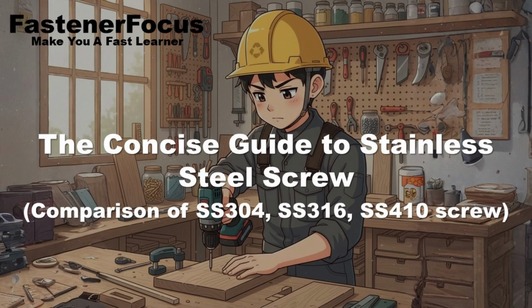So if there's no oxygen in that tight, salty gap, the self-healing passive film cannot reform itself. Exactly. The local chemical conditions inside that tight, oxygen-starved, chloride-heavy crevice change drastically. The trapped water becomes increasingly acidic, and the corrosion rate skyrockets. It's a localized, acidic microtrap where the stainless steel's primary defense mechanism, oxygen-fed self-healing, is disabled.